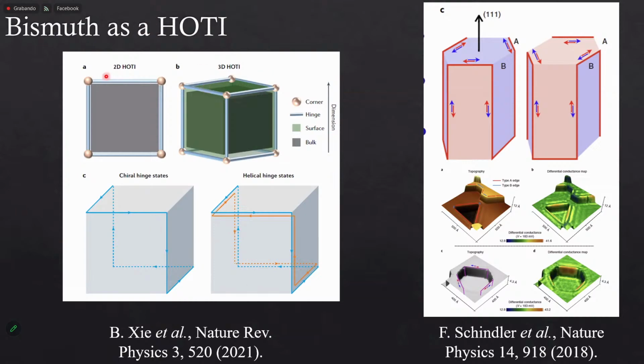So for instance, this is just a cartoon of how they look. And this was proposed in 2017. In 2018, there was already a realization that if you take just 3D bismuth, you have this higher-order phase. So here is a cartoon of how the system should look. You should have states that are not really surface states in 3D, but are actually hinge states. And they were able to measure it using these different platforms here. So they show that you have robust states that live on the edge of the system that present some quantized conductance.